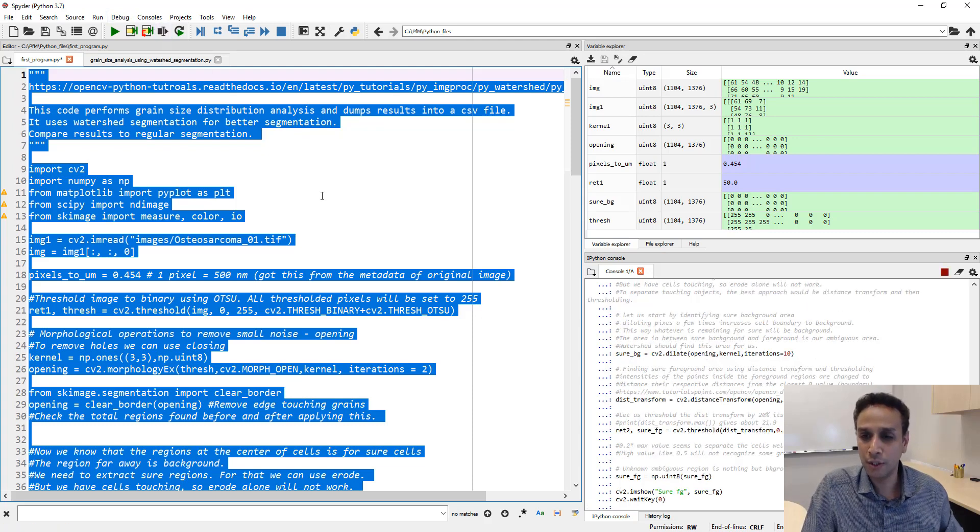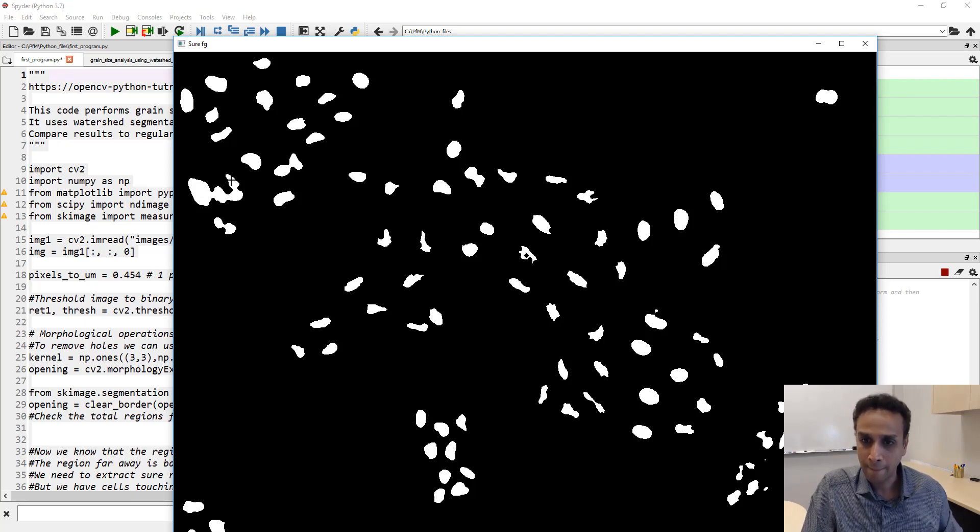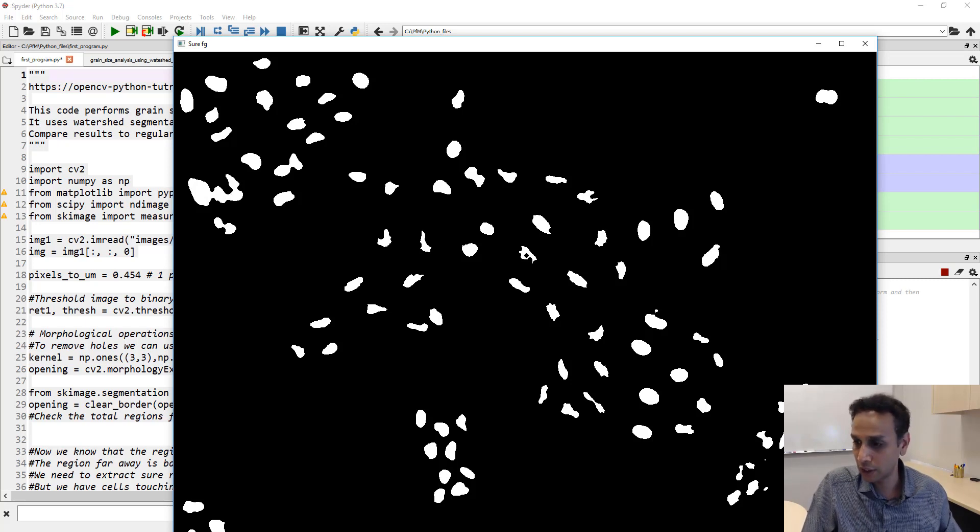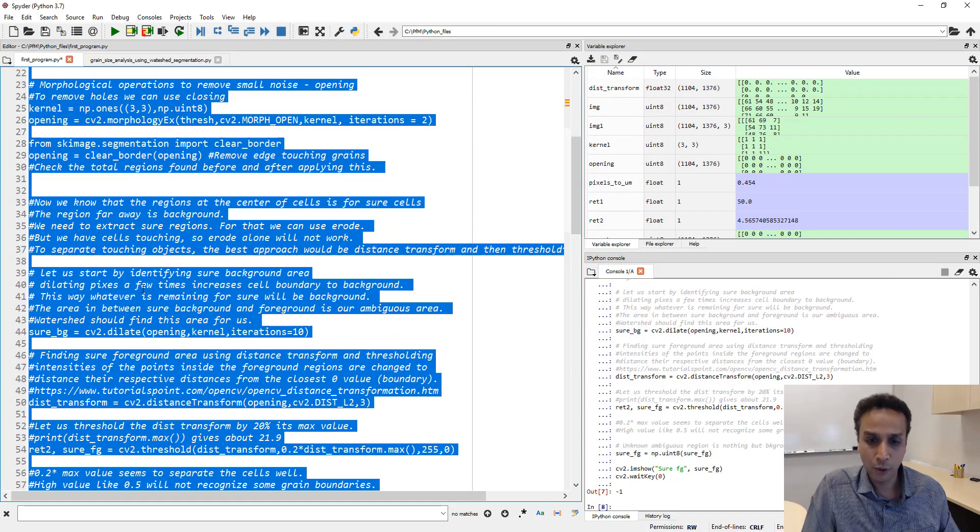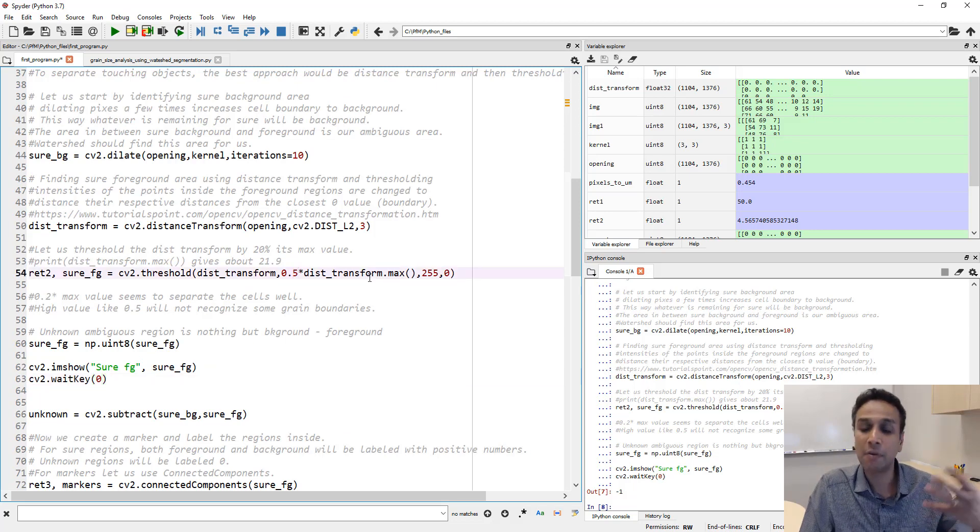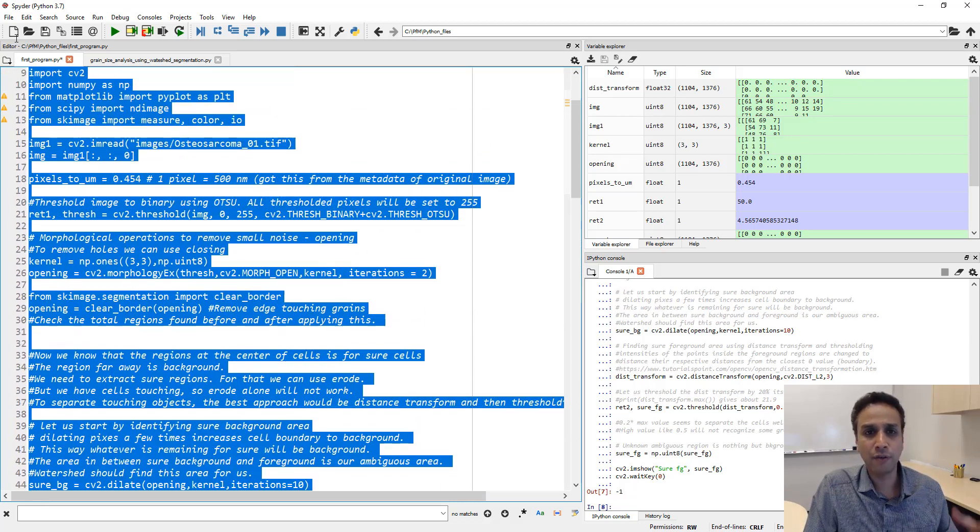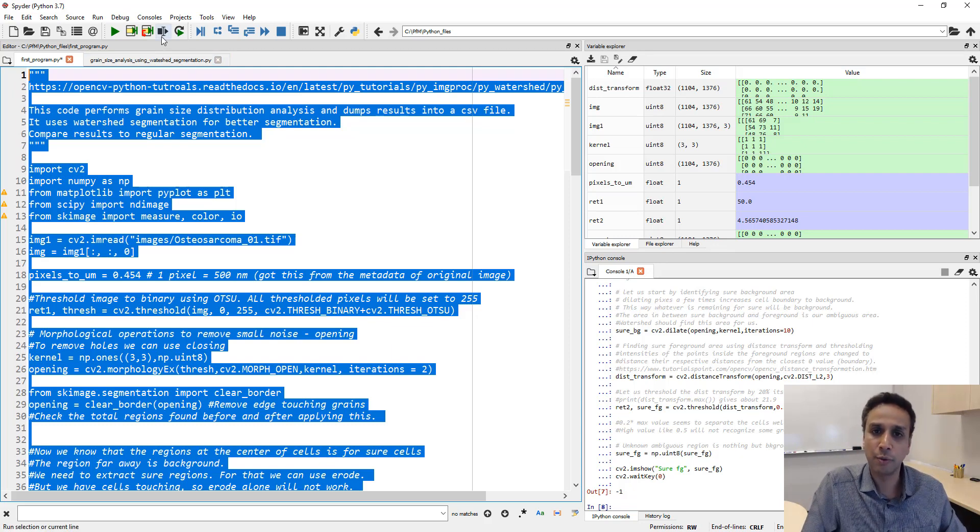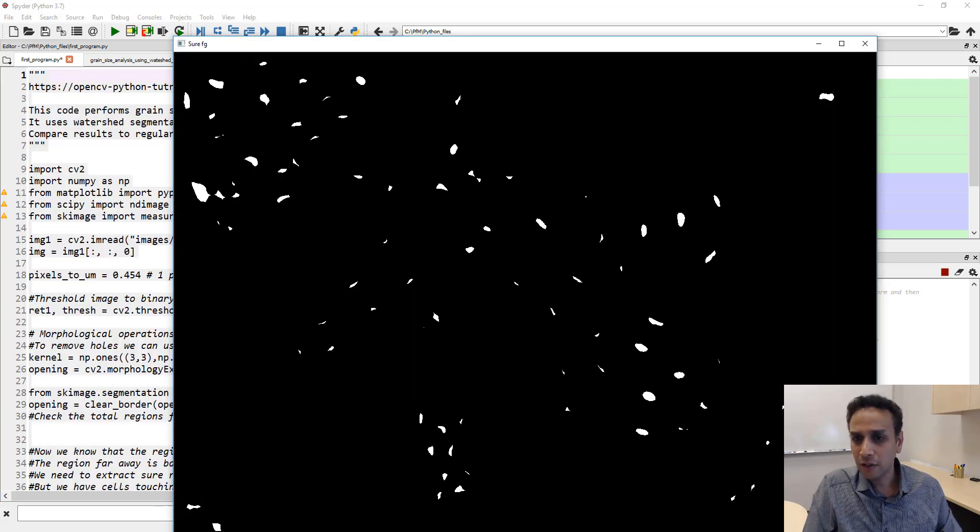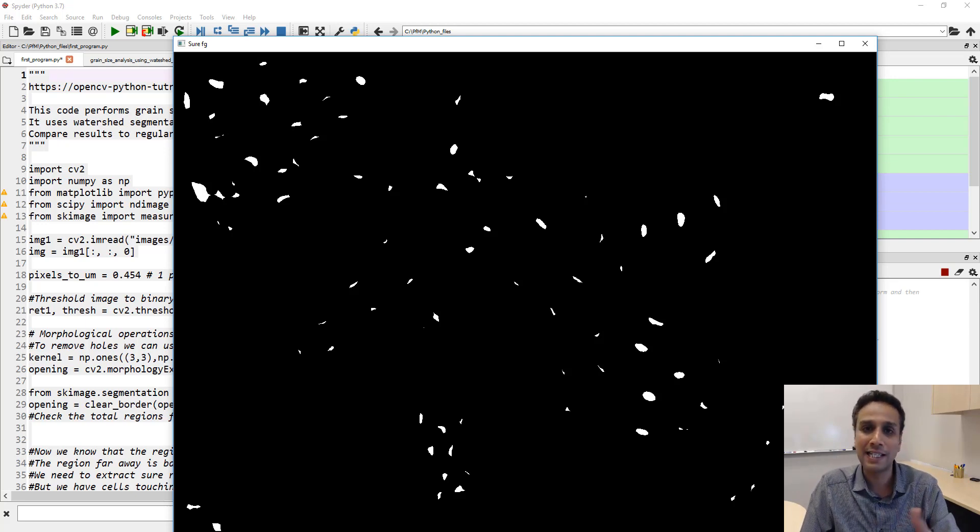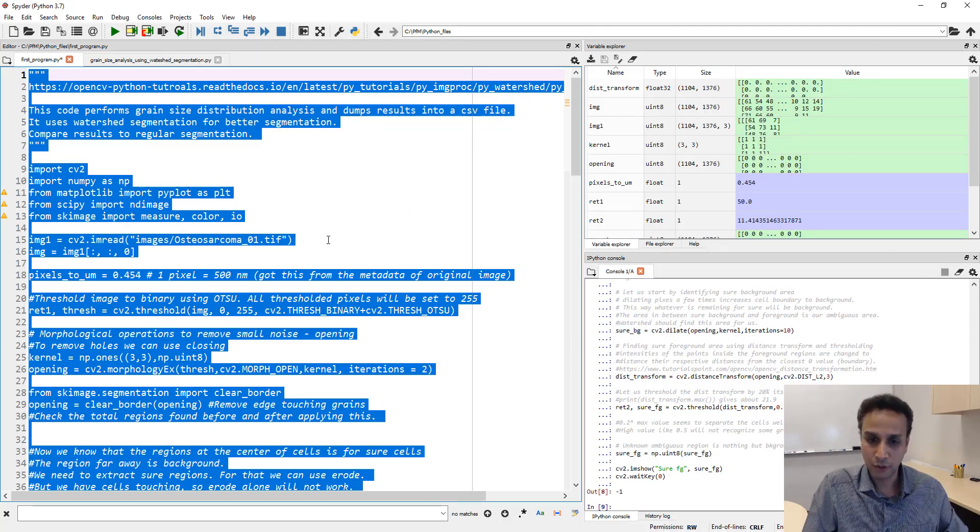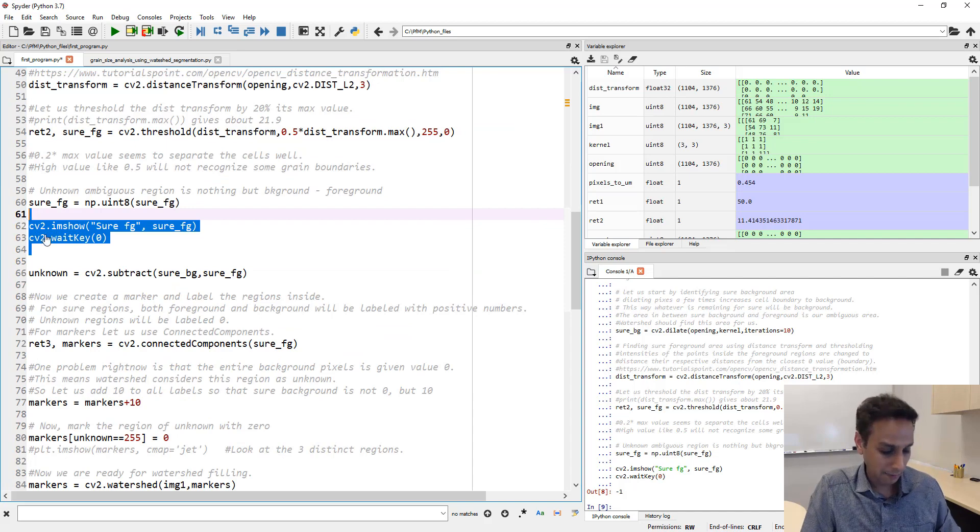Let's run this code. That's for the most part fine. I do not like this, all of these are connected. I want to separate this. Erosion is not going to help because then we'll lose some of these very tiny cells. Let us change this to 0.5 times the maximum value of distance transform. Previously the grains were very large so 0.2 we were okay with that, but now the cells are small so 0.2 wasn't enough. Let's do 0.5. That's okay, we may have a bit overdone it but that's fine. These two are separated, they're all separated, so I'm going to use these as the seeds for watershed. That's why I want to make sure we get this thing right.